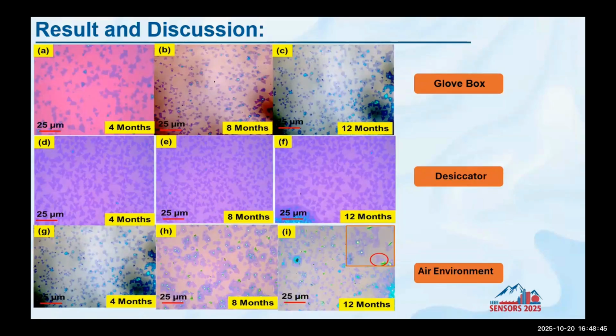On the material side, I deposited the same MoS2 crystals using the same method and kept them in different environments. First, APCVD-grown MoS2 material kept in a glove box in an inert atmosphere. Another set of MoS2 samples kept in a desiccator, a vacuum environment. Another set kept in the air environment. And I did the environmental study over a prolonged time. Here I have shown the result after 4 months, but I have done this study for each month.